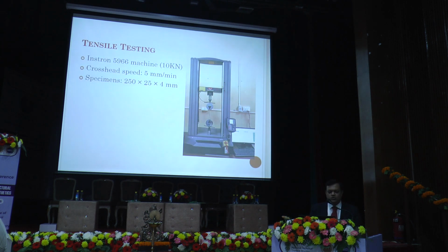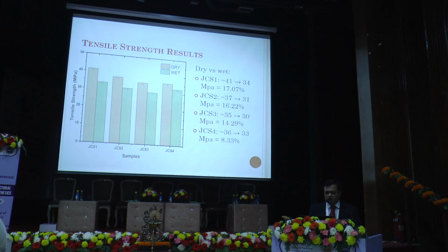Improved fiber-matrix bonding reduces the absorption of moisture. The tensile testing was done in an Instron 5966 machine with 10 kN capacity with a crosshead speed of 5 mm per minute. The results are here. You can see the results for dry condition as well as wet condition. You can see the reduction in strength is almost lowest for JCS4, which had 10% biochar loading.